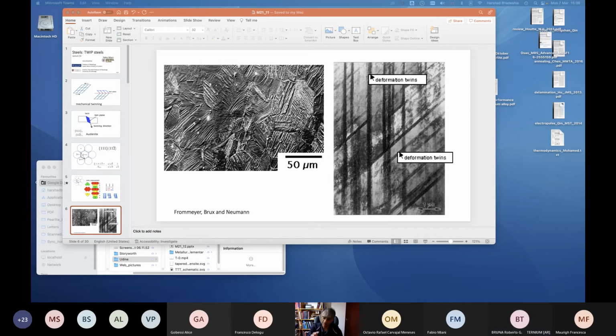And then it's a nanometric size? The original austenite grain size you can see here is like 50 micrometers, but the twinning subdivides it more and more as deformation proceeds, and that gives us effectively a dynamic Hall-Petch effect. So the size is decreasing and the strength is increasing continuously. Okay, very good. Thank you.